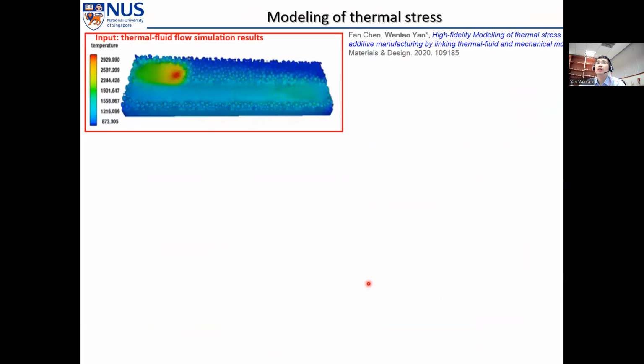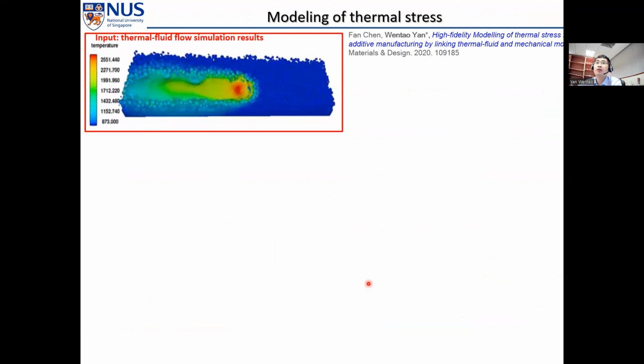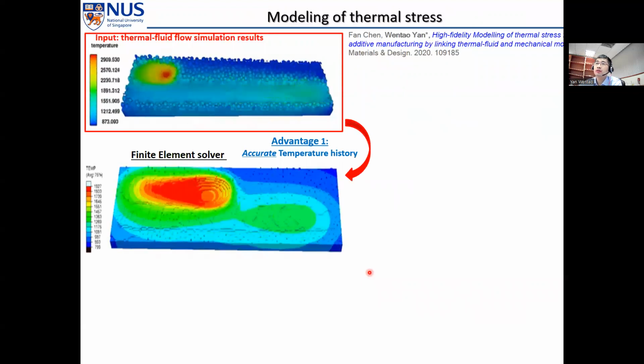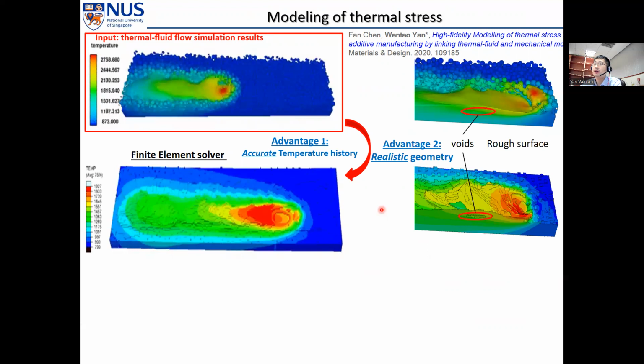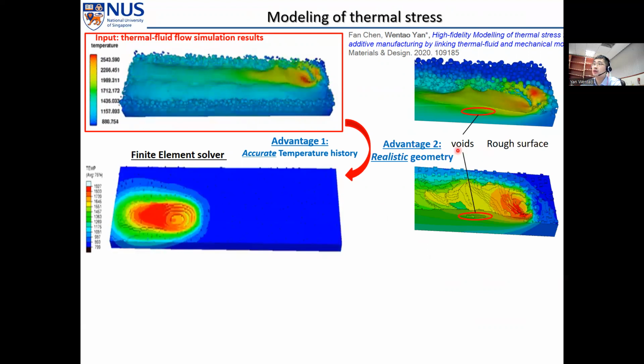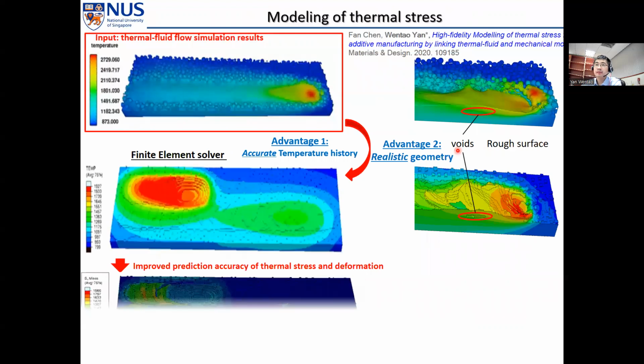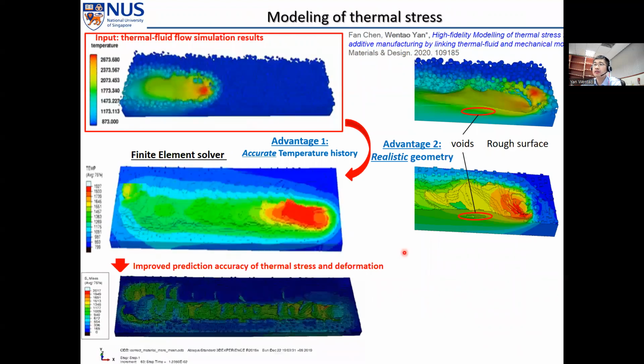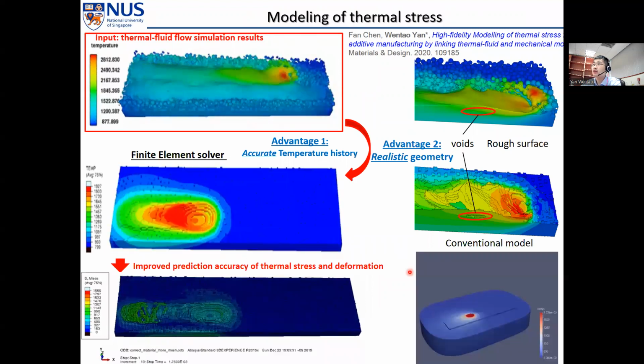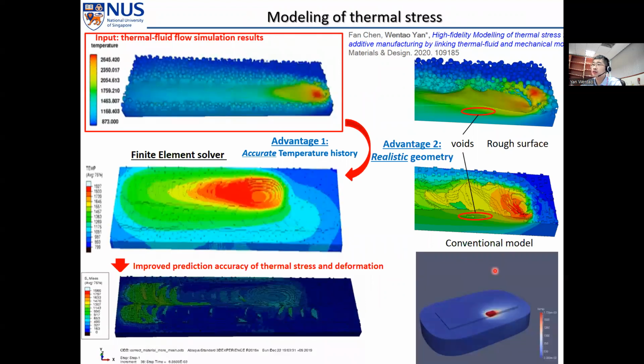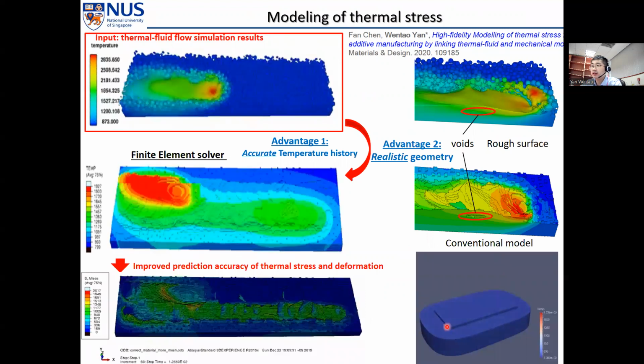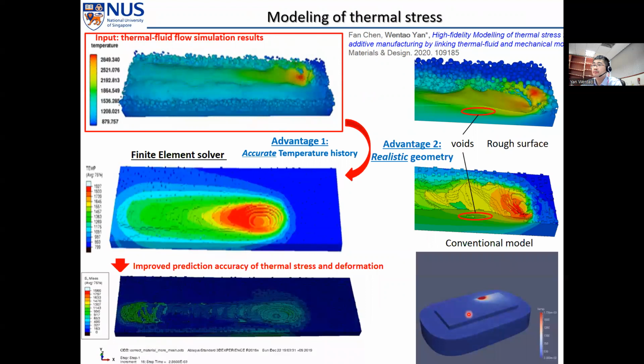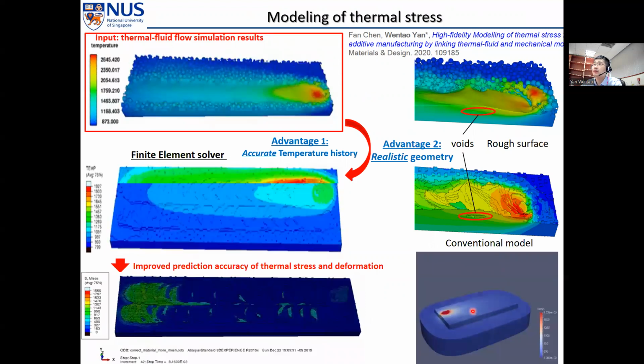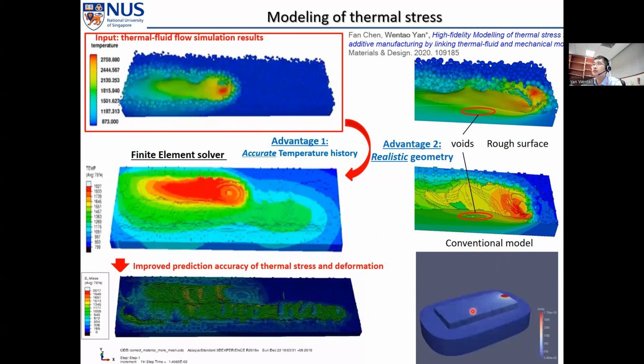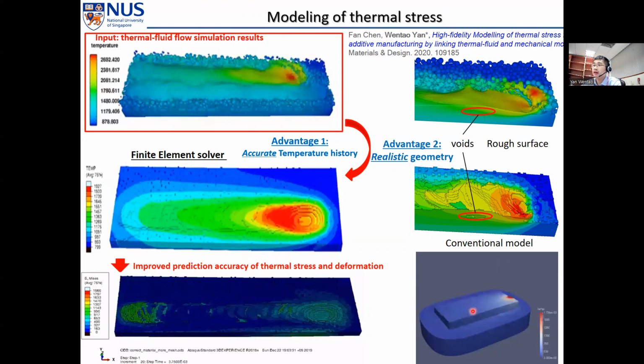So to simulate this, we input the temperature profiles from the thermal fluid flow simulation results into a finite element solver to implement the accurate temperature profile and also the realistic geometry, including voids and rough surfaces, so that we can improve the prediction accuracy of thermal stress and deformation. In comparison, you can see this is a conventional thermal stress model where the surfaces are perfectly flat and the temperature profile is not so accurate. Then the error may be relatively big.